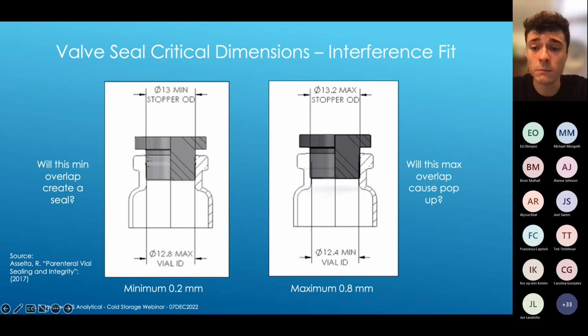On the other side, the other extreme, let's consider the smallest vial inner diameter of the mouth with the widest stopper plug outer diameter. And so when we have these other dimensional extremes, does this stopper even fit into the vial? If it does, does it pop back up out of that vial as a result of too much compression in this interference zone? Or do we start seeing deformation of that elastomer, let's say wrinkles or puckering, as a result of this aggressive dimensional overlap? And so by taking measurements on a wide number of stoppers and a wide number of vials, we can put those components together to specifically evaluate the risk to integrity at the dimensional extremes that these components may come in.